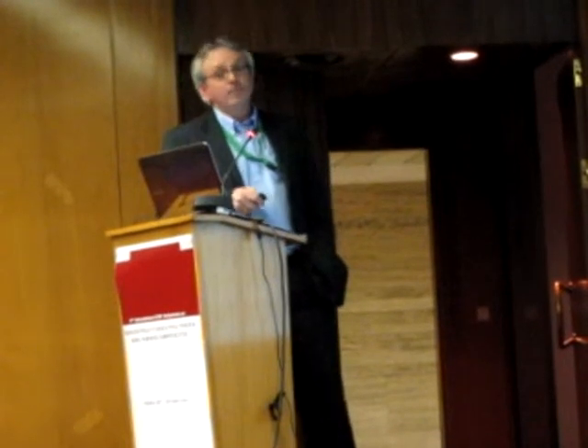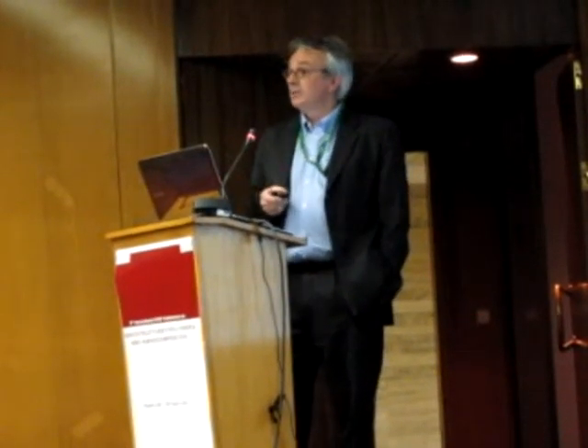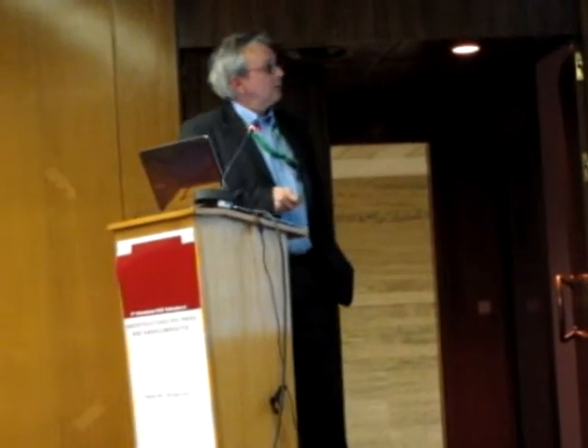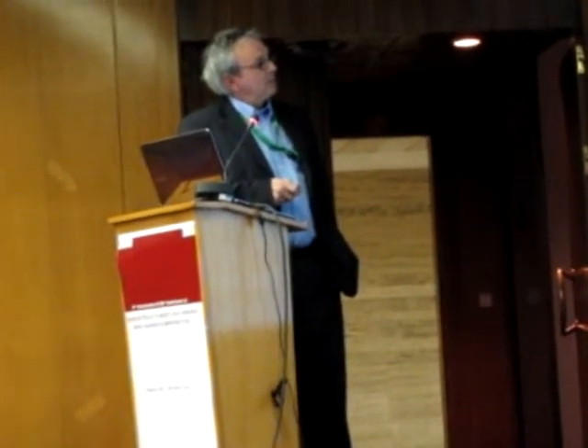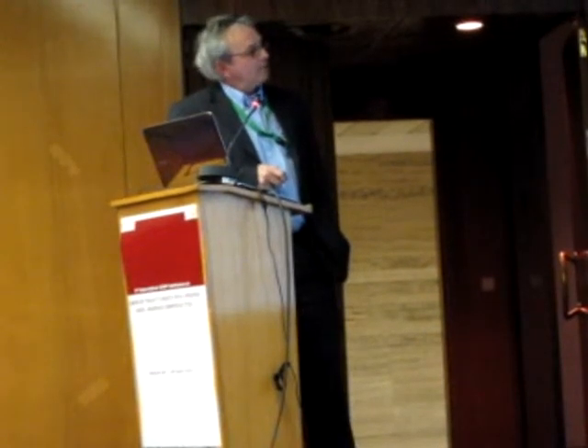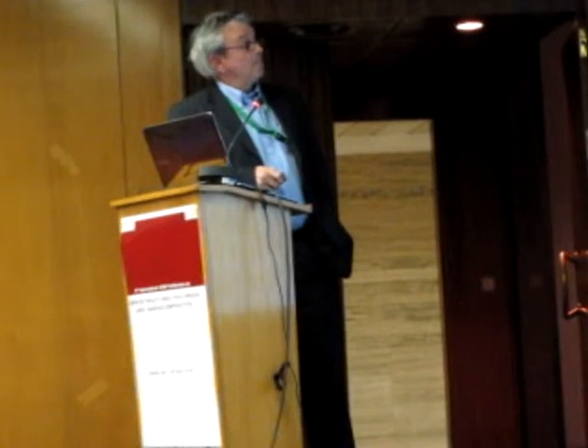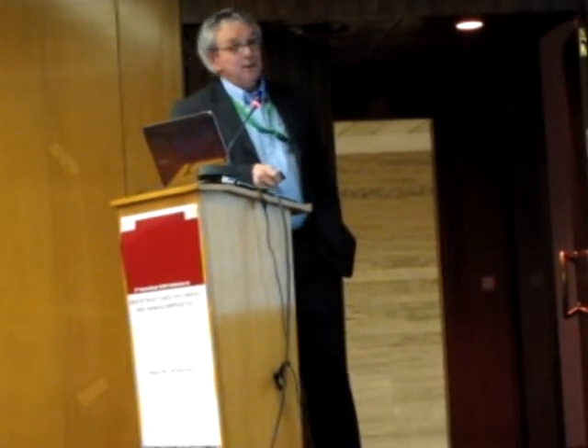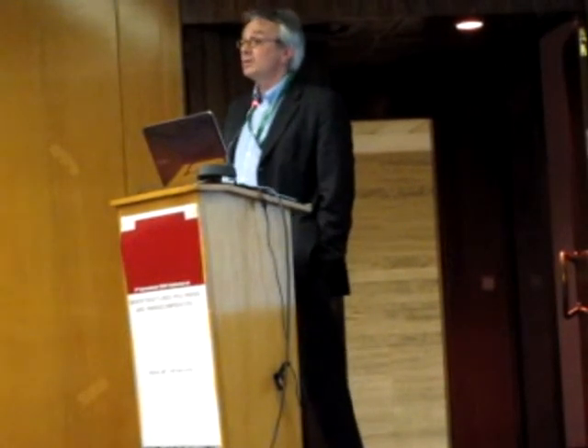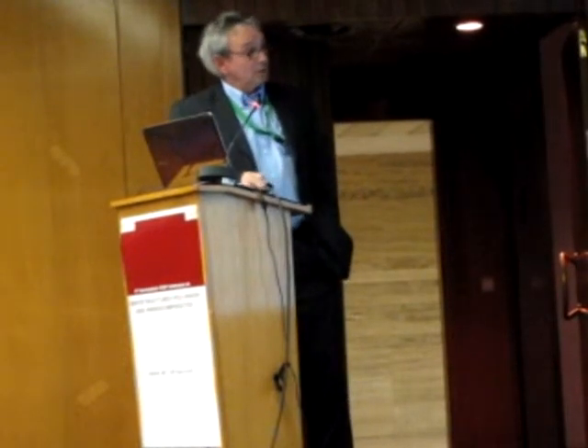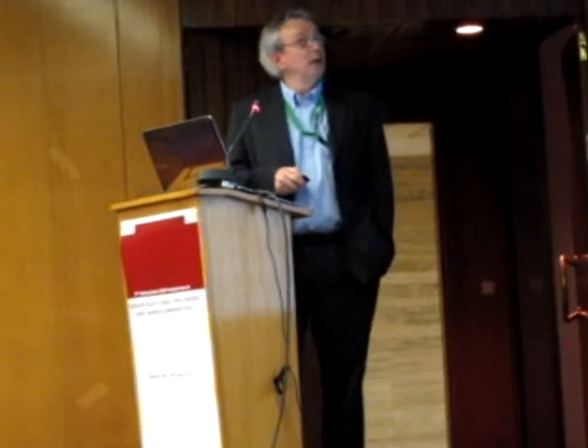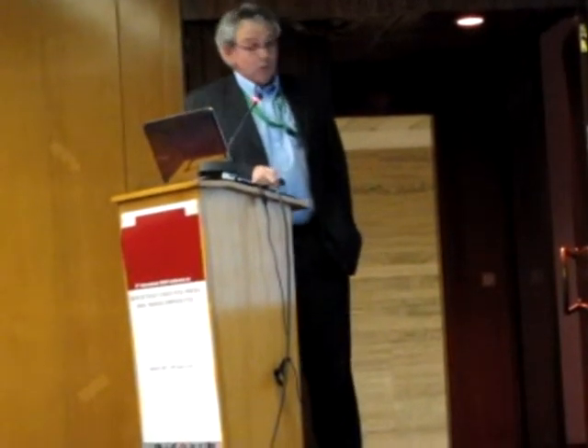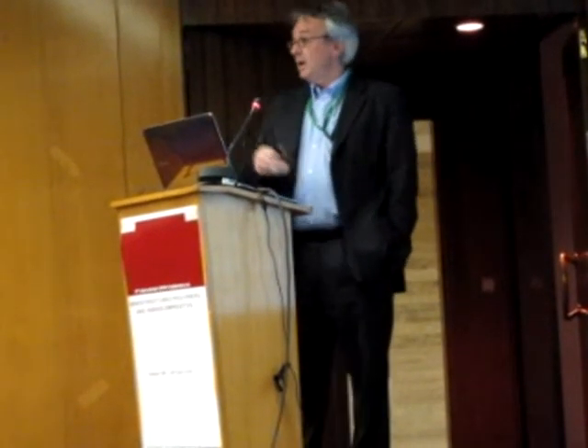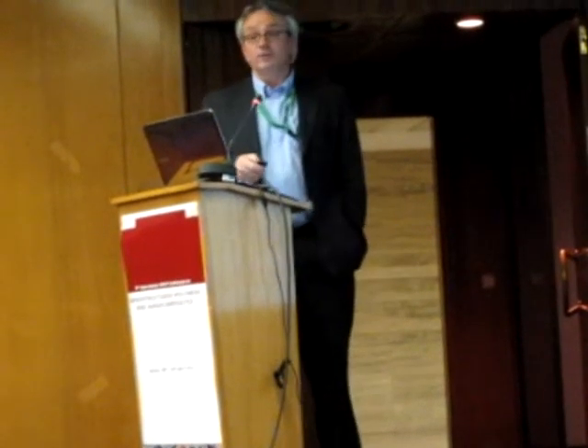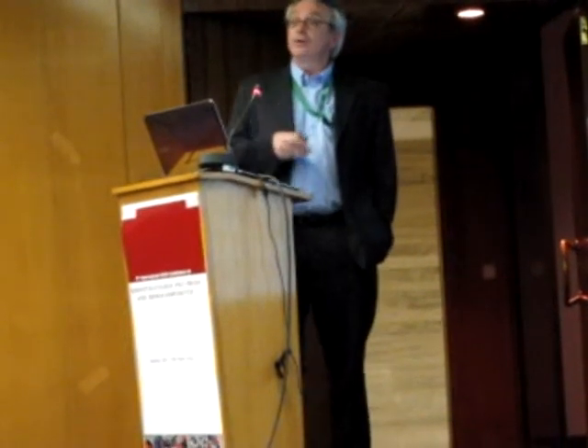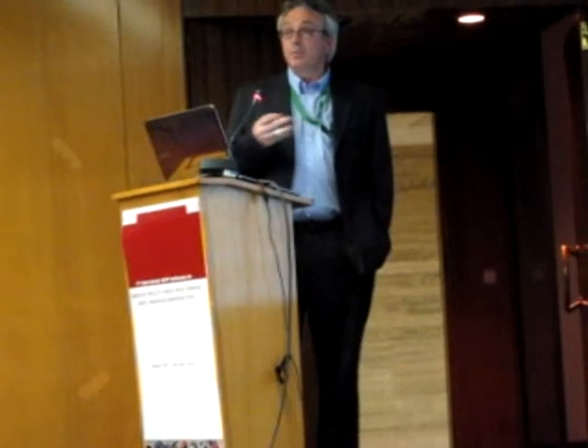Now, if we change the functionalization of the silica, so the interaction between particles, the gel is not formed at the same level. Looking again at the pure lactide, here you have the fumed silica, 5% methacrylate modified. Now you have a gel which is not so strong, and the system goes like that. The G double prime at the end is above the G prime, which means that the system remains a viscoelastic fluid and behaves as a thermoplastic system, which is again shown by the rheology of the PLA fumed silica at the end of the reaction. So we changed completely the way, and we were able to process PLA with 5% silica for a given specific surface by changing the interaction between particles. The surface chemistry of the silica is very important to be able to process the system.